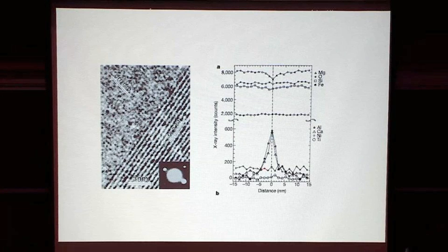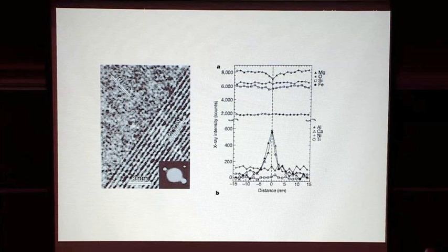Well, it's actually interesting because this is AEM analysis, and it may be that the AEM analysis doesn't have the spatial resolution to get the grain boundary exactly right. So if anything, it exaggerates the width of the grain boundary. This looks to be about 5 nanometers across here, but if I asked Takehiko Hiraga about this, he'd probably say that the grain boundary is about 2 nanometers. So how much does this affect the bulk composition? Well, he's written about that. It's interesting. For anything that has any compatibility in the lattice at all, it's irrelevant.